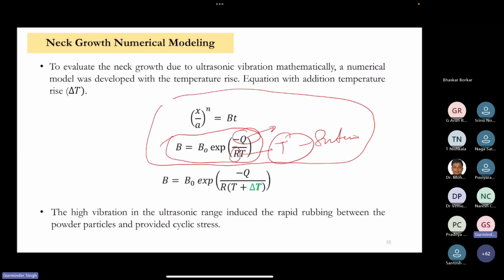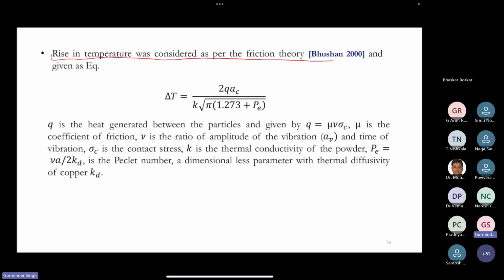Now, as I mentioned, in the experiment we have observed that, instead of just the sintering temperature, we are having some local temperature rise, delta T, which was due to the ultrasonic vibration. So we have added this delta T value here. We have taken this delta T from friction theory. This is a rise in temperature from a friction theory given by Bhushan in 2000, which says that when you have two surfaces in contact and they are vibrating against each other with some coefficient of friction and some amplitude of vibration, there will be some delta T rise in the temperature. So we have measured the coefficient of friction, ratio of amplitude, and time of vibration for this process, and we came up with a delta T value.